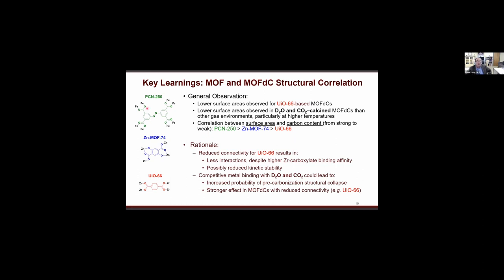The rationale to explain this is a reduced connectivity for UiO-66. Also the linker itself is smaller, with fewer interactions, despite higher zirconium carboxylate binding affinity, because there are fewer interactions in the middle there, and also possibly reduced kinetic stability of the MOF. So competitive metal binding with D2O and CO2 could lead to an increased probability of a pre-carbonization structural collapse, for example, hydrolysis or decarboxylation. So a stronger effect in MOF-derived carbons with reduced connectivity, like for example UiO-66.